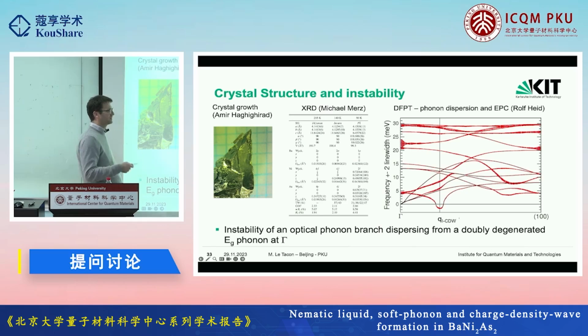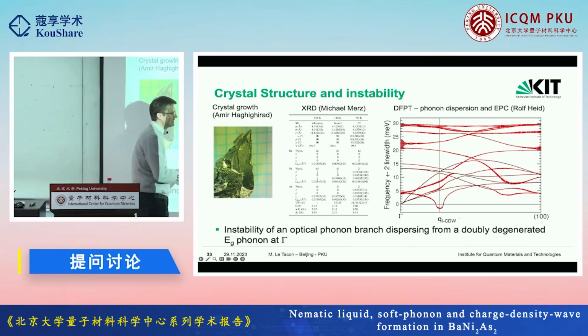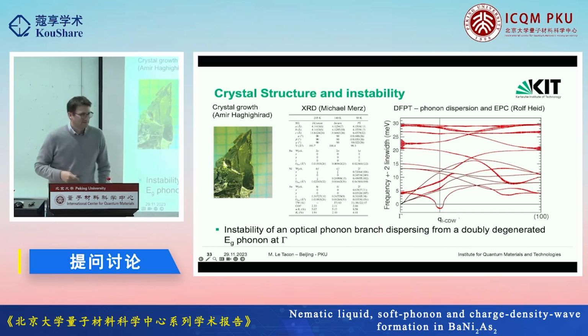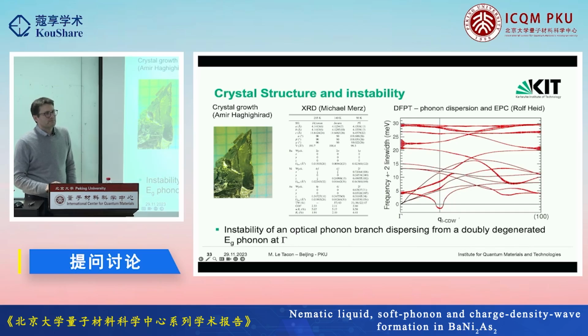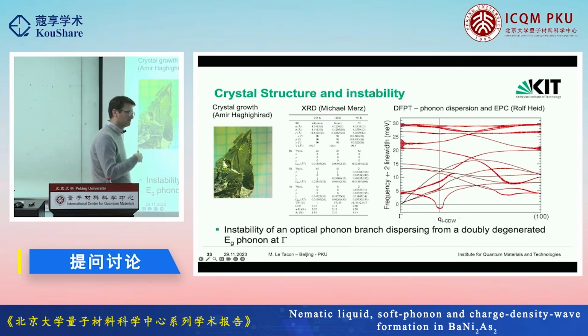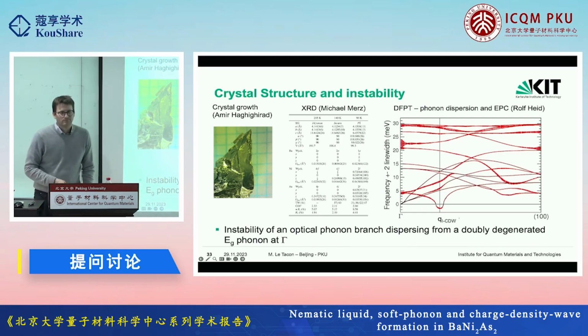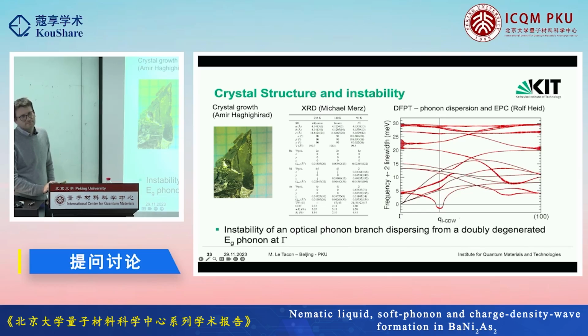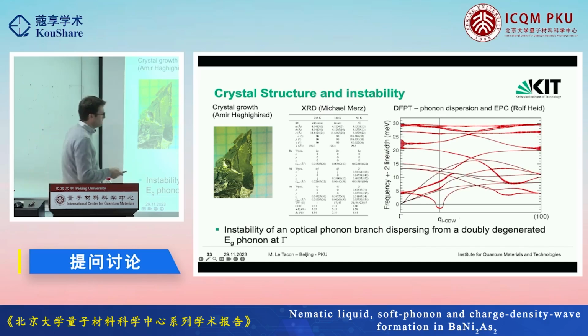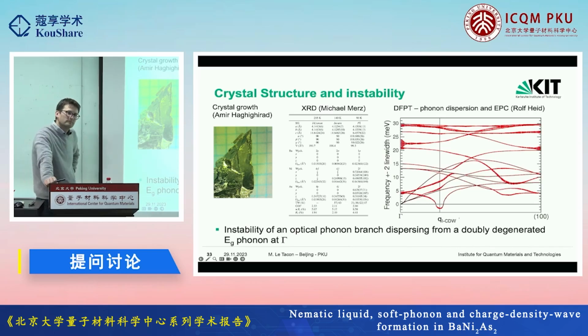And Rolf has been trying to play a bit around this and try to suppress the thing, and he also couldn't really. So I agree with you. It's nice that the theory predicts the instability, but the theory doesn't tell us here where the instability is coming from. Well, I think, for example, they should be able to compute the dielectric function. That will tell you, for example, the electronic contribution to the phonon. Yeah, actually, this is a good point. Well, we haven't done that yet. Although you showed that the total density of states and some other things didn't show a strong feature at this wavevector.